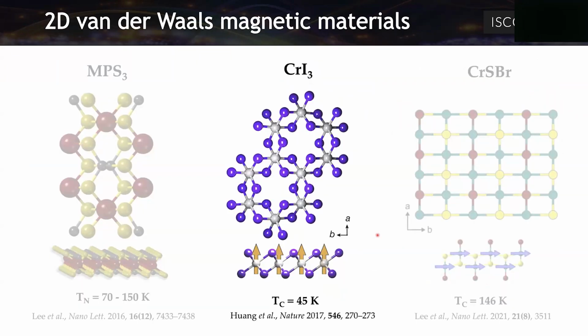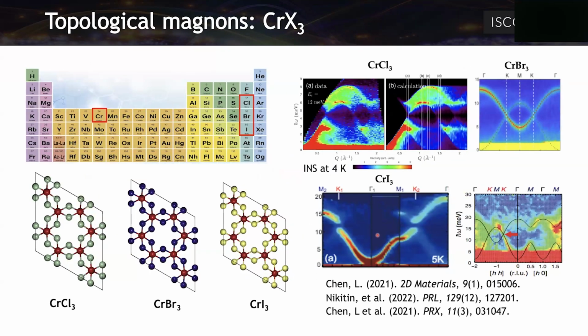Then we have been also working with chromium iodide 3, chromium chloride 3 and chromium bromide 3. These systems are also interesting for magnonics because in the magnon dispersion there's a Dirac cone, similar to the Dirac cone in the electronic properties, but in this case in the magnons, because they have a hexagonal unit cell. And especially in the case of chromium iodide 3, this Dirac cone is open. There's an opening here, and this leads to topological magnons. So they are magnons that are more robust in this case.